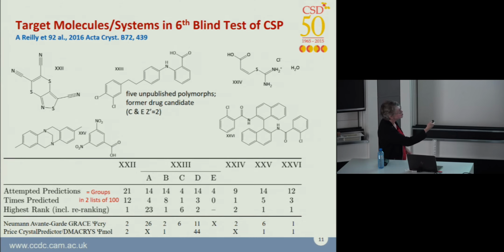But the real star of the show was one of the pharmaceutical industries provided 5 crystal structures from their screening. So we had 5 polymorphs there. This is Avant-garde Simulations' results, which are very good, using, and they're the people that developed using periodic DFT. They initially developed their own dispersion correction for doing that. And the other line, I'm quite proud of how my group did. One member of the group had each target, and for the PhD students, that's a chapter in their thesis, doing this blind test. You have to give in your predicted structures before you get the answer, and then there's a meeting, and the paper therefore has a list of all the different approaches that have been done, and we learn a lot from comparing them.